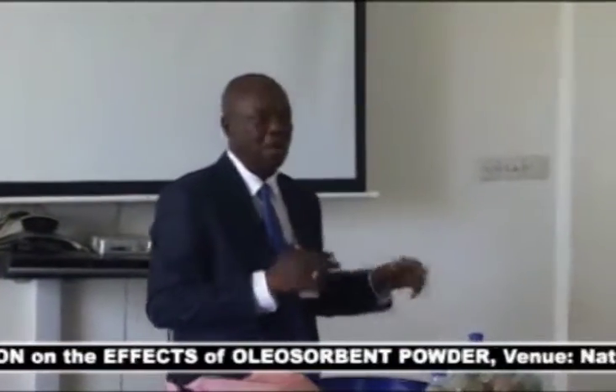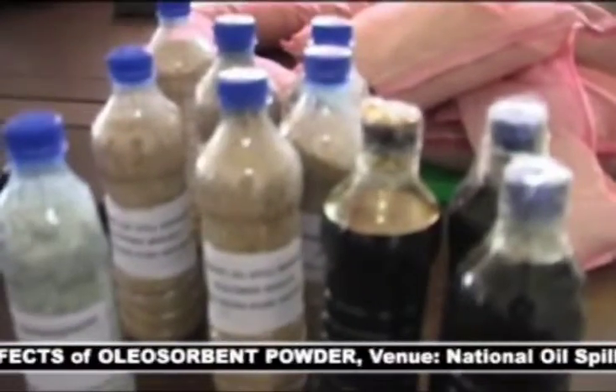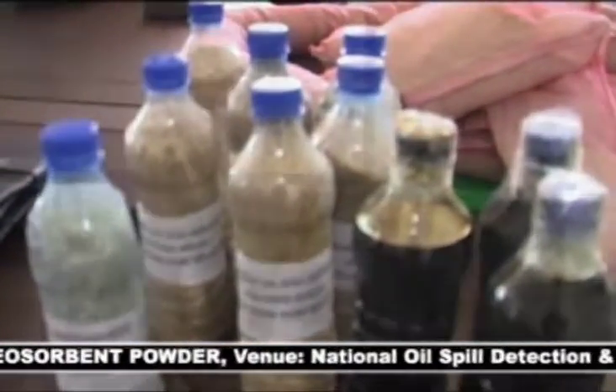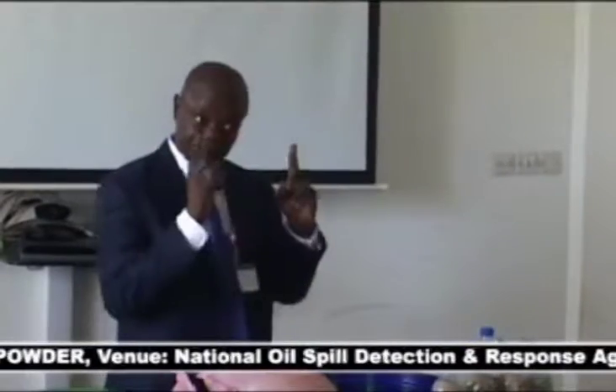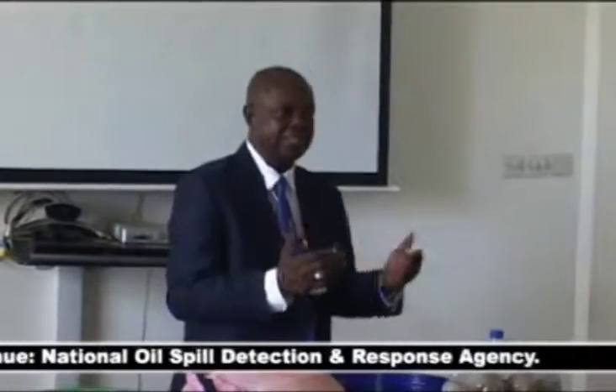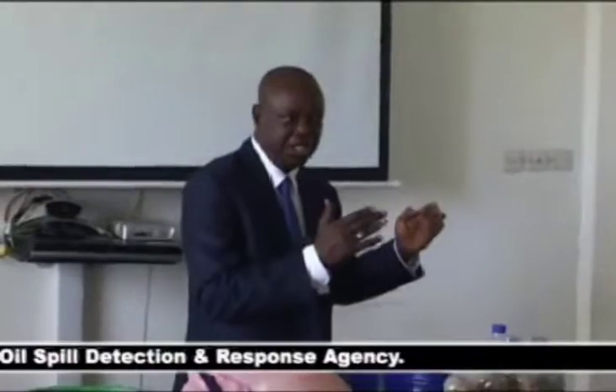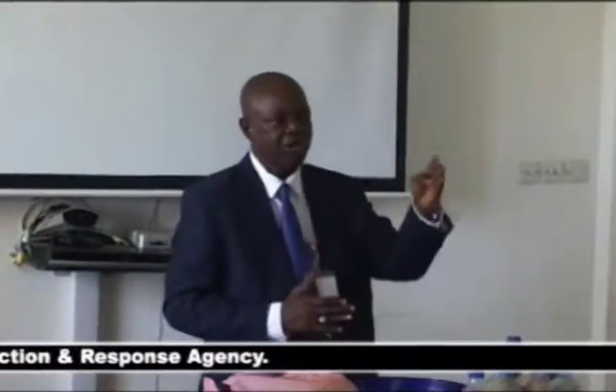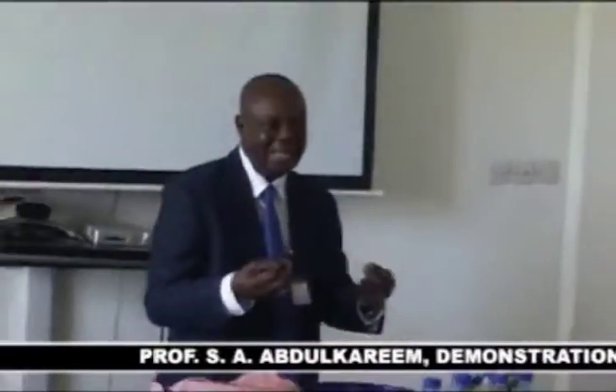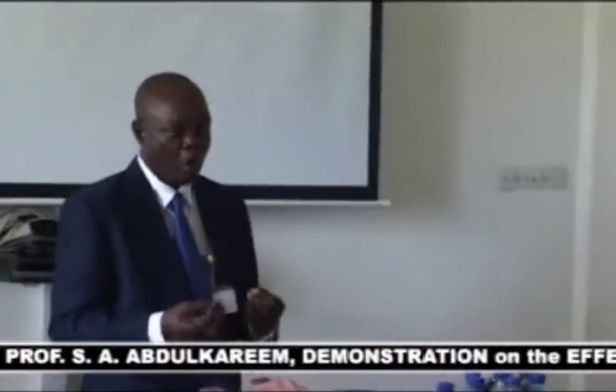So what I have here now is a material that is still polyethylene, because it's from the polymer sachet. The difference now is that the property has changed from original oleophobic, hydrophobic to now hydrophobic, oleophilic. By oleophilic I mean this material is now craving to absorb 6 to 10 times its own mass of oil or organic material.